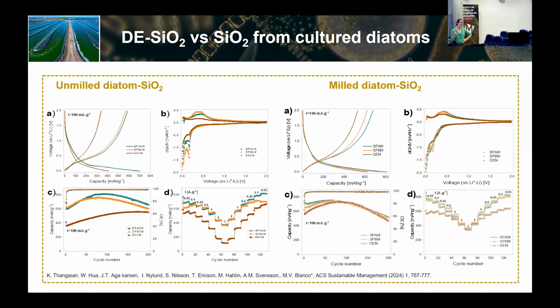When we do the ball milling of the material, then we don't gain much in capacity, almost all the contrary. And this also is a thing we are facing, that is that particle agglomeration will go smaller in size, and you have other things that are happening there. So not much gain with the change in particle size. But we have some feeling that, okay, we can get better capacity, morphology clearly affects performance. So this is kind of some indication that this could be a good material.